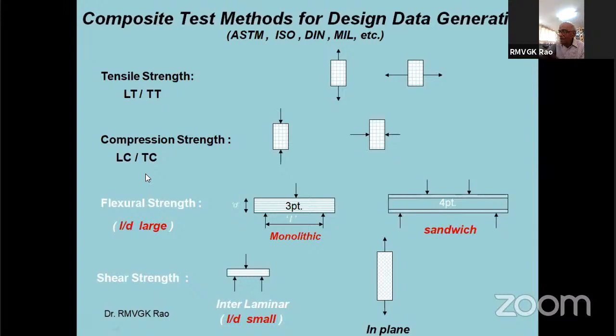And there are other tests, but at the bottom, you have what is called in-plane shear. That is, you take a 0 and 90 degree fabric and cut it at 45 degrees and pull it. So you are actually testing the matrix shear between the fibers. That is very important for assessing the damage tolerance of the structure. And compression is also very important, especially, as I said, in the aircraft wing spar. The top goes into compression, the bottom goes into tension in full flight when the aircraft is under lift force. Therefore, tensile strength anyway goes into the composite structure when it is undergoing bending or tension. So these three properties have to be generated on a vast number of specimens.